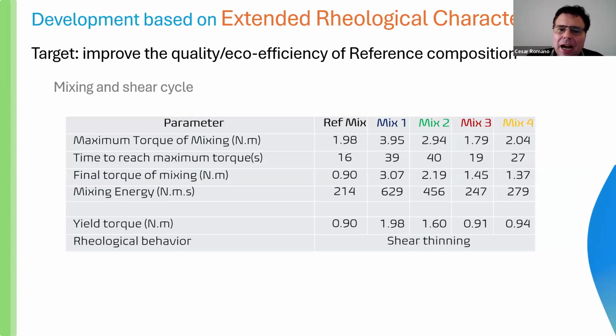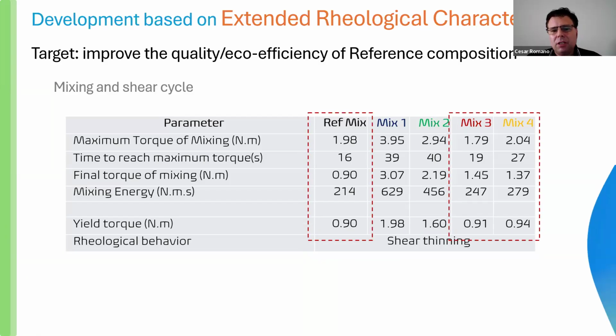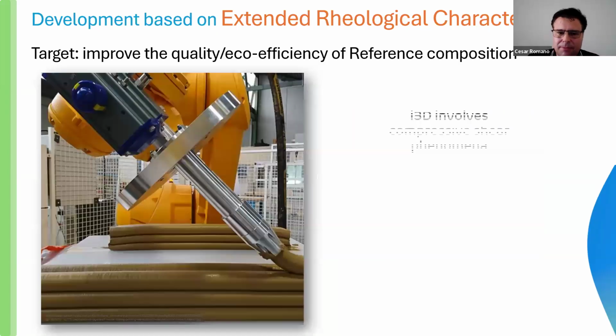And here we have a table that is summarizing all the results, and it's possible to see that all of the compositions presented shear thinning behavior. That is not the case here because it was not pumped, but we want to have this rheological behavior if you want to pump the material. And we have similar results for the rheological parameters when we apply the rotational rheometry to evaluate the mixing and to evaluate the rheological behavior, the yield torque, and things like that.